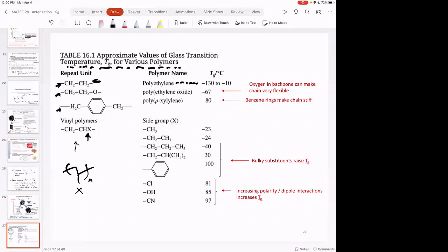But why do we use polyethylene in milk jugs and packaging and other stuff if it has such a low Tg? The Tg of minus 10 means it's a liquid at room temperature. So why do we use it? Because it crystallizes and all those crystals lock polyethylene in place. So it feels hard because of the crystals at room temperature. But the amorphous fraction of polyethylene is still liquid at room temperature. That's why it's got really high permeability. That's why we don't use polyethylene in water bottles, but still, that's a really interesting fact.